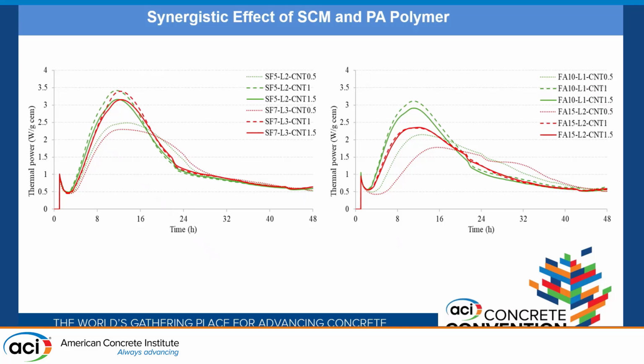And then we ran some additional experiments, trying to look at, because of that effect, whether we can synergistically bump up the dosage of SCM in conjunction with CNT. With normal mixing, we know the dosage is typically capped around 0.5%, but in this case, can we go higher, 1%, 1.5%? The result is promising. So basically, what we have in the observation is if we use SCM as a carrier just to attach the CNT to its surface and use that to deliver into the cementitious system, we can get the dosage quite high without completely changing the rheology.